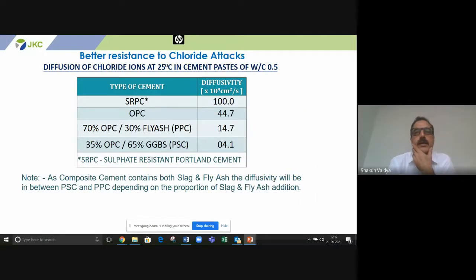So chloride attack, as I told you, will corrode the steel. So a chloride diffusion test is conducted, and it has been noted that SRPC, which again is an OPC cement, is 100%. OPC is around 44, 45, and you can see that OPC with GGBS and OPC with fly ash are also less.